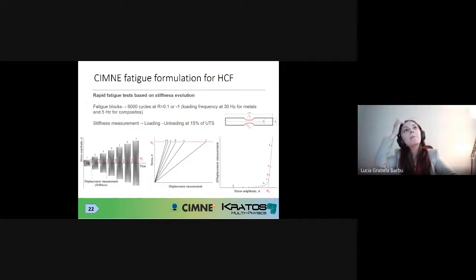Okay, now something else that's very interesting for the high cycle fatigue domain. You see, high cycle fatigue has quite a big problem regarding the experimental time needed to have a full characterization of a material. You need to do a lot of experimental tests. Basically, for each SN curve, you need about 19 specimens if you want to be scrupulous and also have statistical effects accounted for. And this takes a long time.